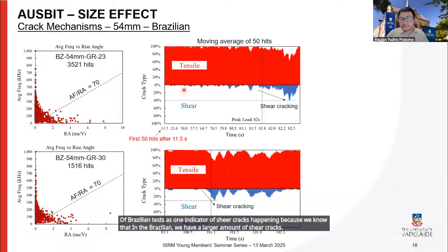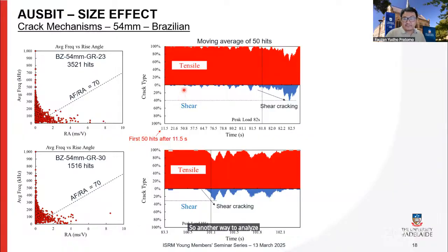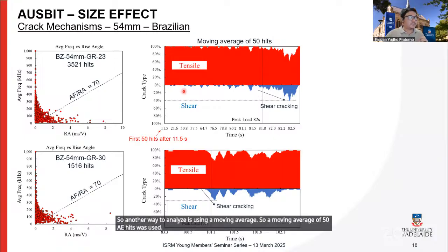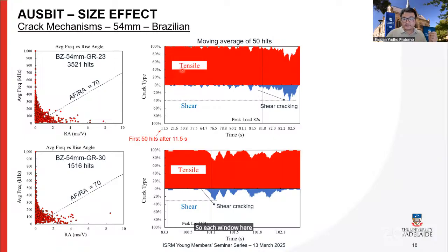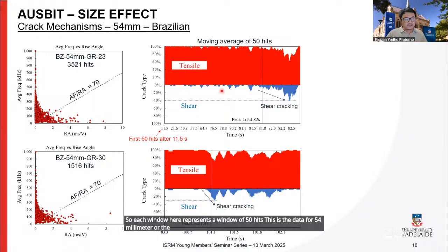So another way to analyze is using a moving average. A moving average of 50 AE hits was used, so each window here represents a window of 50 hits. This is the data for the 54 millimeter, or the medium-sized Brazilians. Shear cracks were concentrated when the failure happens.